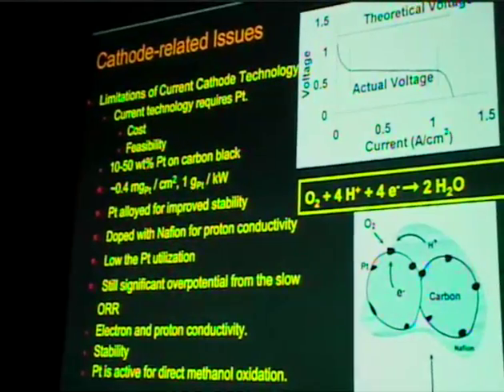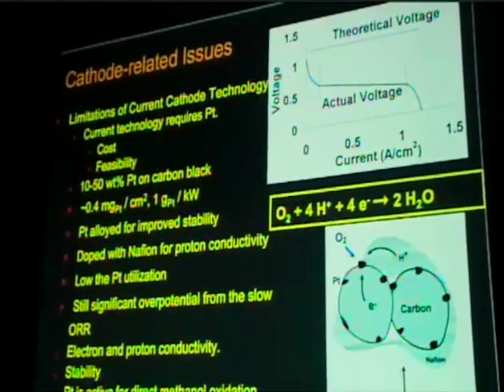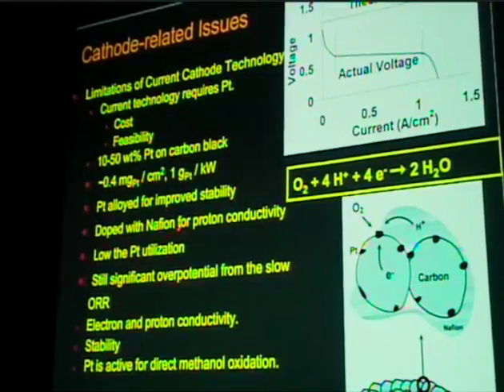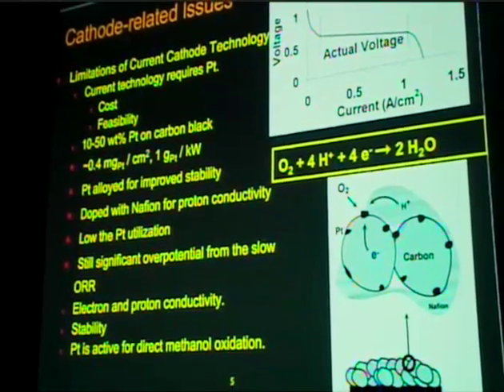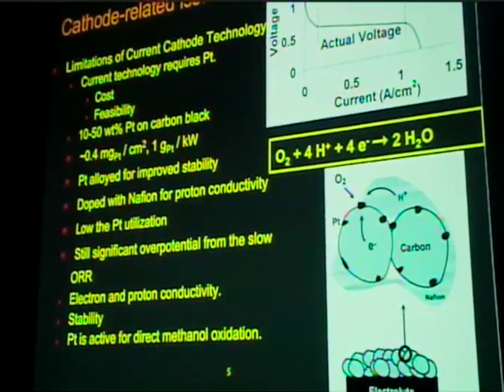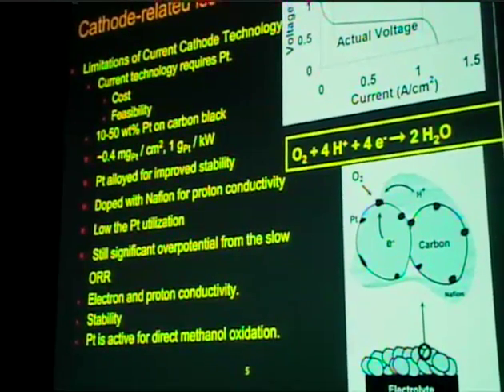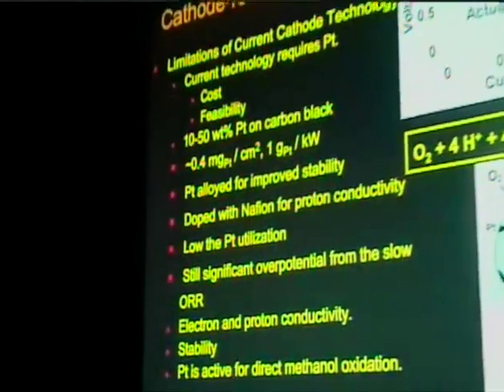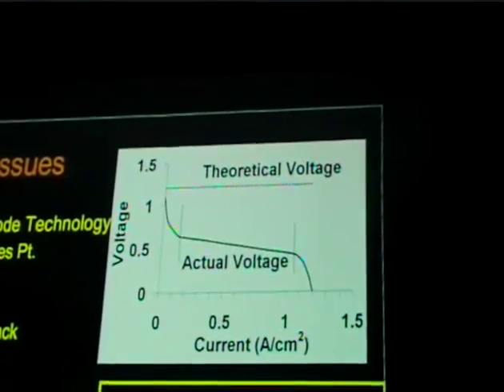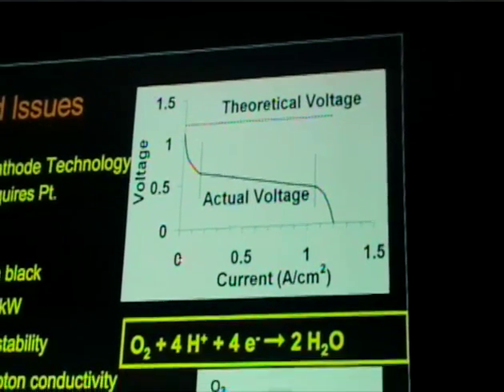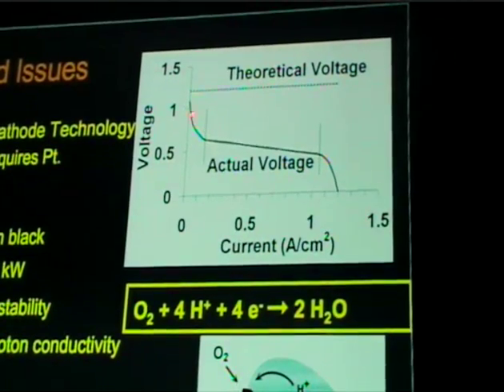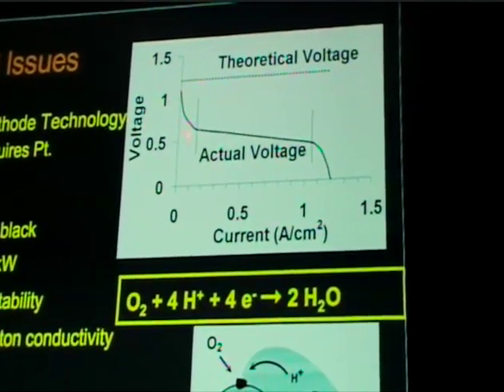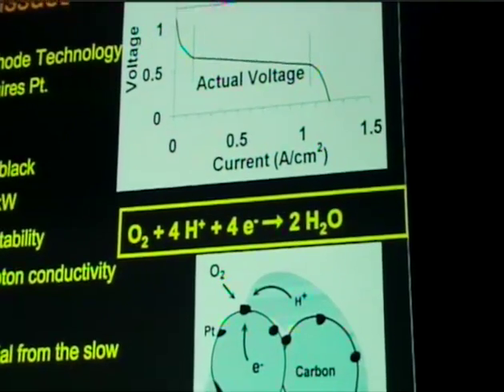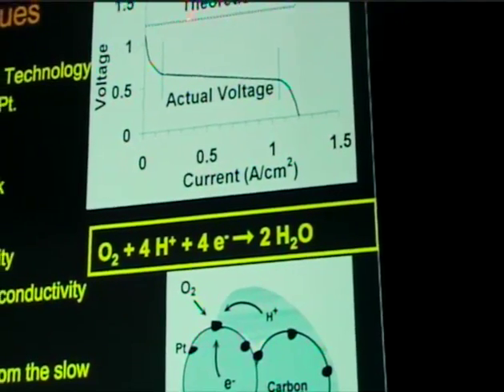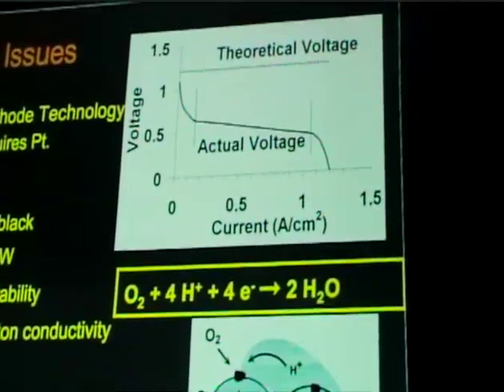And the platinum alloy is being used for improved stability, especially on the anode side. It is being doped with Nafion, which is the polymer electrolyte. Platinum utilization is quite low. And if you look at the voltage versus current diagram, typical diagram from a PEM fuel cell, as you can see, as we start drawing current, the voltage drops as expected. But if you look at this first sharp drop, that's really the kinetic controlled regime. And this is because of the slow kinetics at the cathode side.